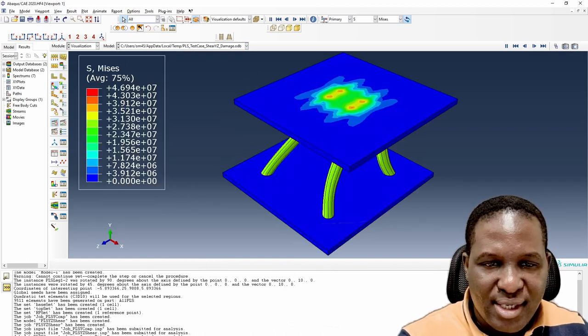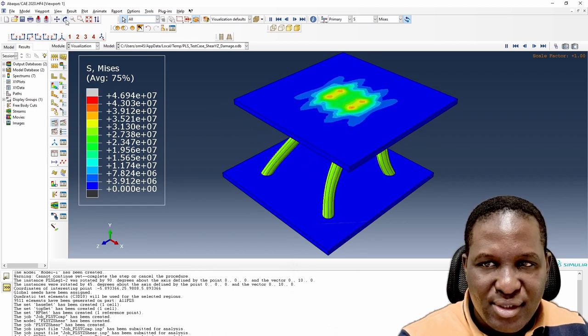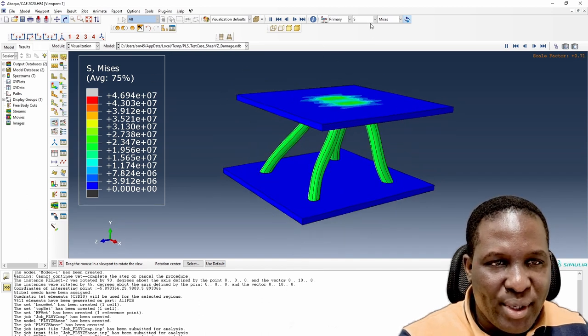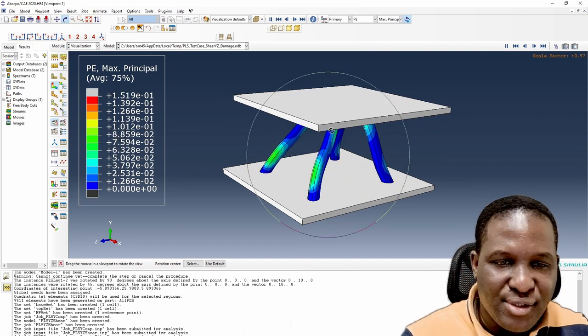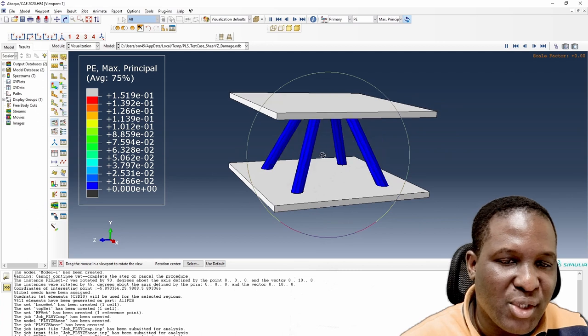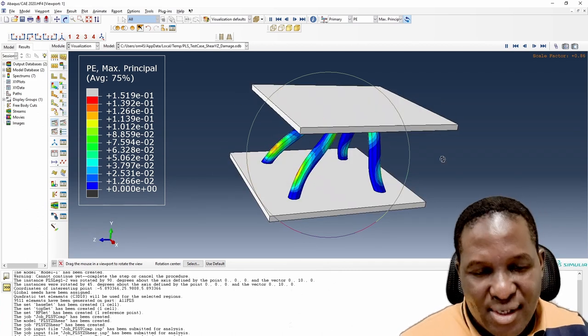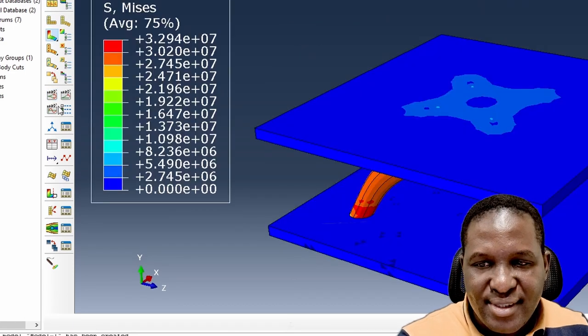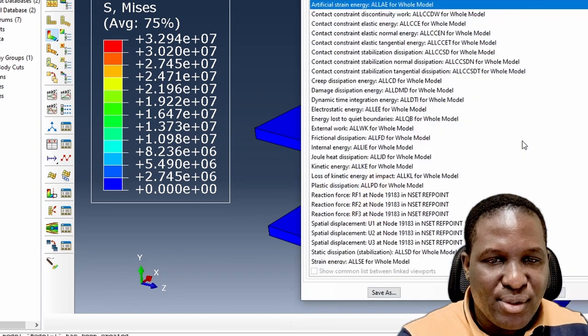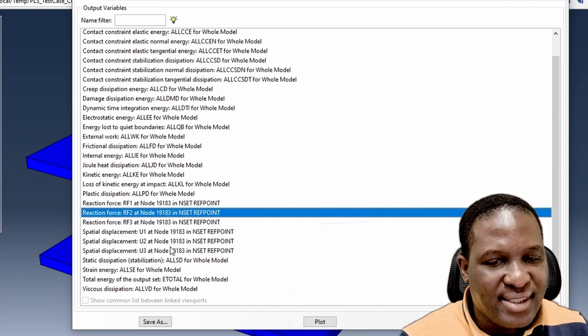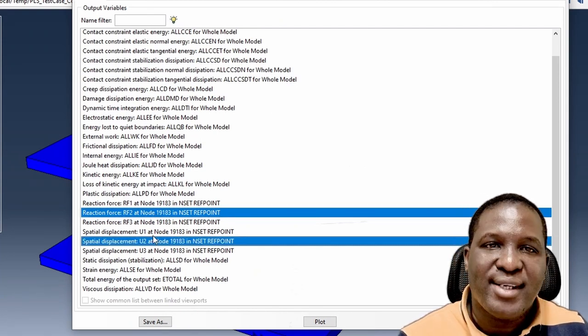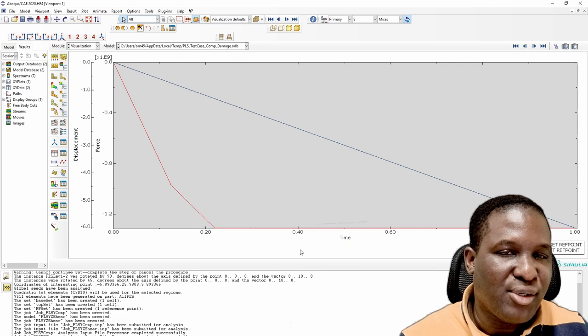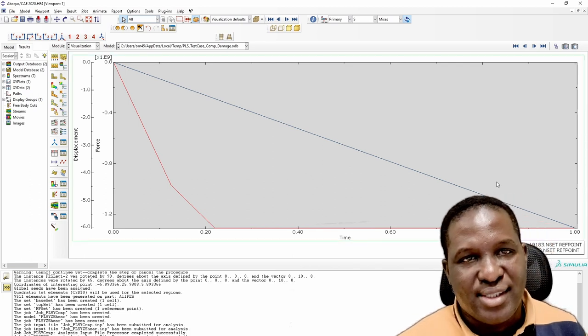For the shear case, we get a similar kind of result. Animating this shows the von Mises stress as the structure deforms. Moving to the plastic strain, you can see what's happening to each of the legs as they undergo plastic deformation across the board. Finally, for the stress-strain plot, we go back to the compressive case, click on the history output, and extract the reaction force in Y and the Y displacement to combine and generate an elastoplastic stress-strain plot.